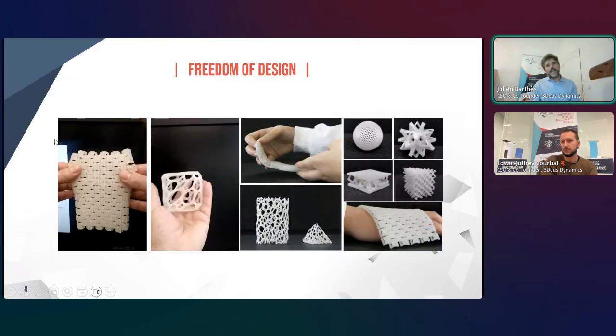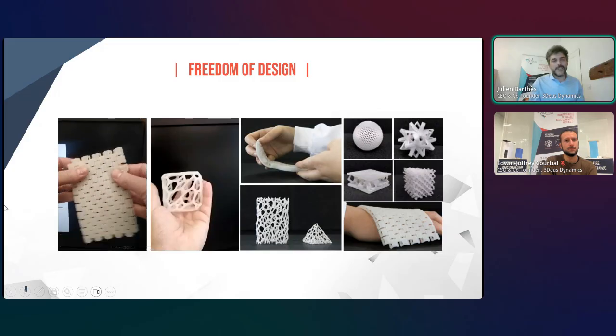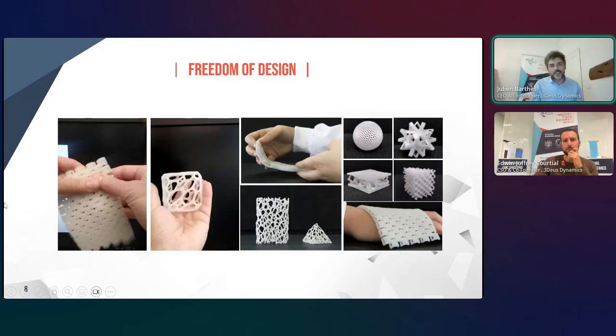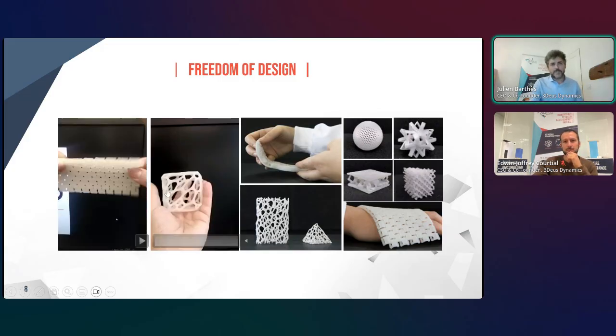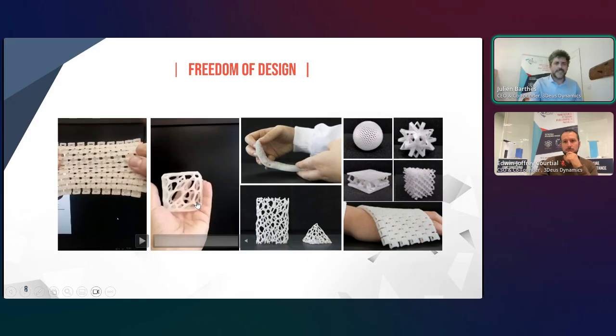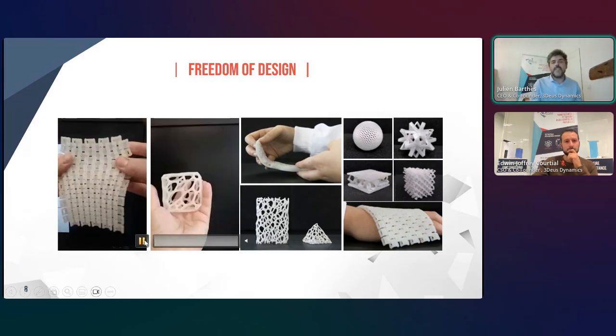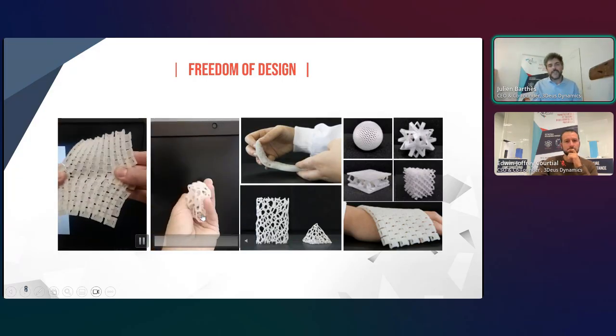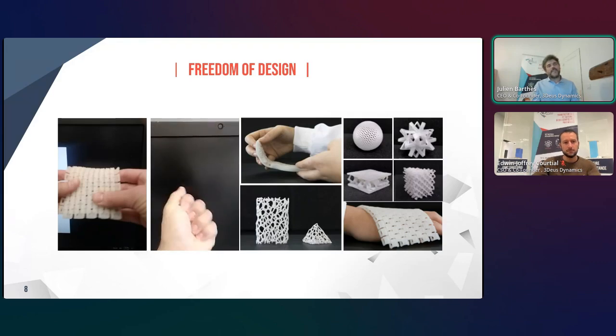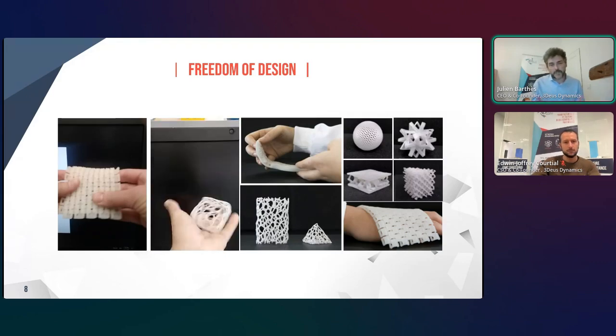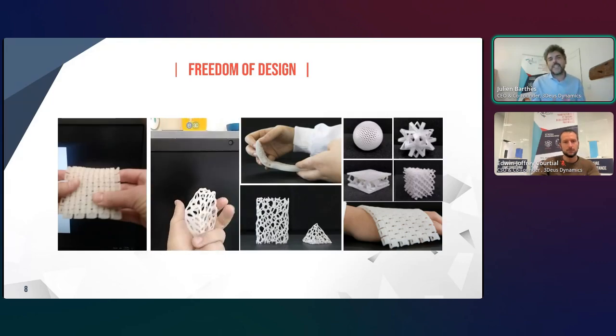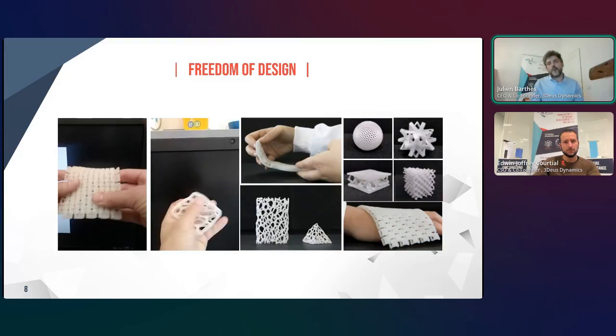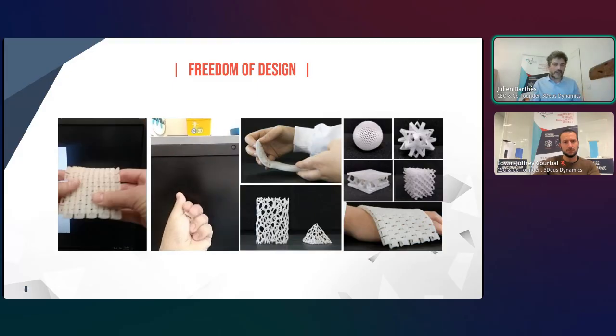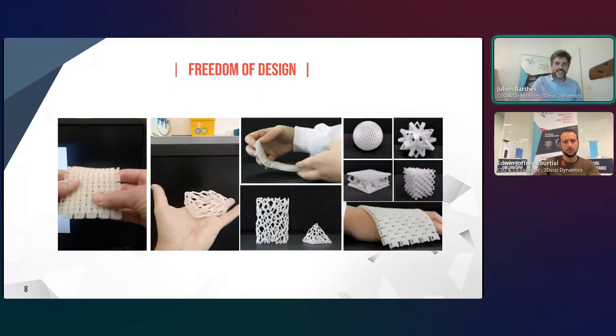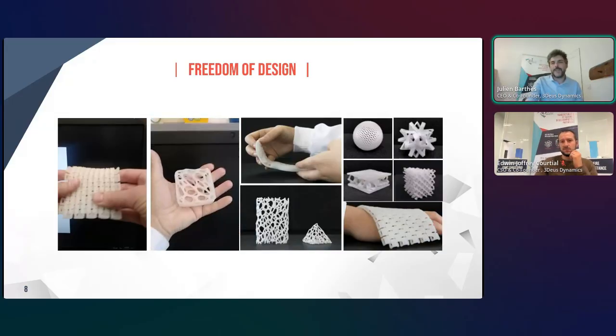So just a few highlights about the freedom of design that you get. You can see a few videos. So this is the textile-like structures. You can see you can print all this in one go. Then totally self-supported material, you will see. And what is great is that in terms of mechanical properties for pure silicone, you maintain between 80 and 90% of the properties of the raw material, so the injectable silicone. And you can see a full range of different geometries that we can achieve with this.